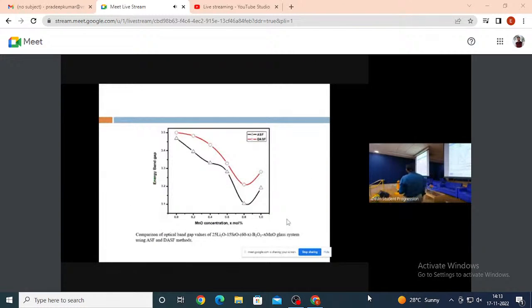Here, this is the comparison of optical bandgap values of the prepared glass samples using the Tauc, ASF and DASF methods. In these three methods, the same kind of trend was observed while determining the indirect bandgap energy values and optical Urbach energy values. From this, I can conclude that there is excellent agreement among these three methods.